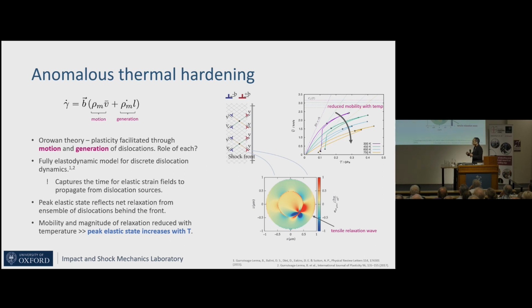Dislocations, of course, they are the defects, they're the agents of plasticity. And all you need to really know about this equation here, which represents sort of the plasticity that can form in a material, is that it's mediated by 2 factors: motion of dislocations and also generation of dislocations. And so what he was able to show is that under those conditions of extremely high strain rate, the effect of a dislocation appearing, popping into a material, moving around, isn't felt throughout the body instantaneously. It takes time, which is associated with the characteristic sound speed of that material. So here you can see an actual wave front of a dislocation that's moving, and this wave front wouldn't be felt by the shock front until it had communicated forward enough.